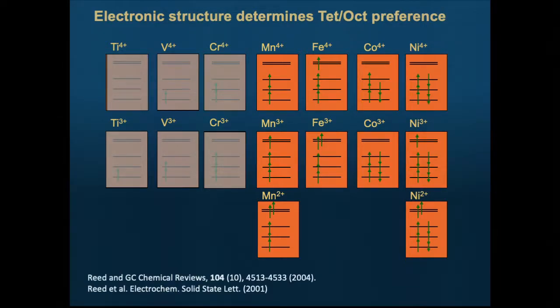Okay, then you look at things like iron 3+. This is the worst. This has 5 spin polarized electrons, so this is largely ambivalent about its coordination. Iron 3 can do tetrahedral, iron 3 could do octahedral. So this is a terrible ion to work with in a battery because it moves all over the place. Okay, so iron 3 is out, and therefore iron 4 is out as well. What about manganese 3? You sort of think maybe that would be okay. The problem with manganese 3 is that it disproportionates. It makes manganese 2 and manganese 4 sometimes, and manganese 2 is terrible. 5 electrons, it's a half-filled d shell. This thing moves all over the place because basically it's ambivalent about its coordination.